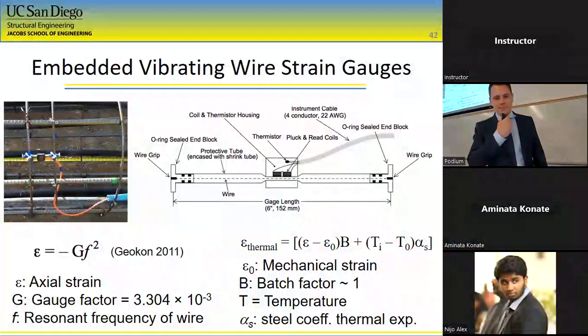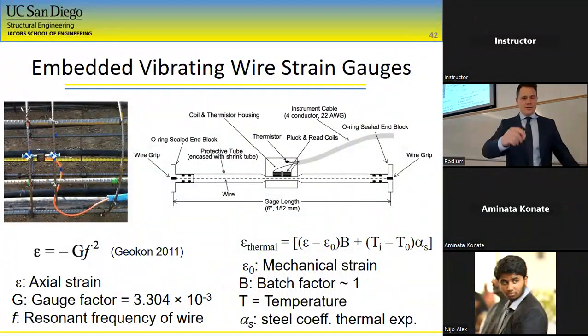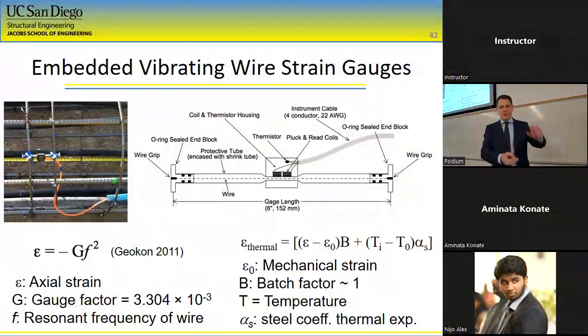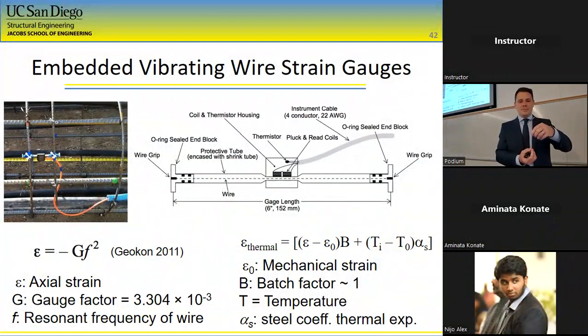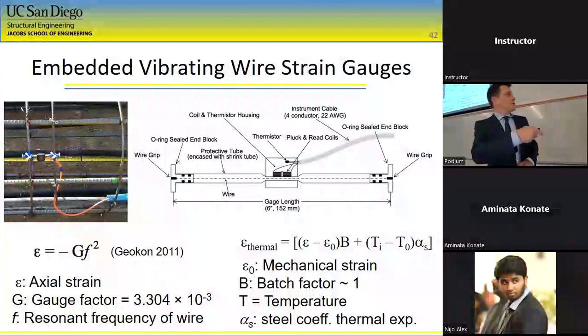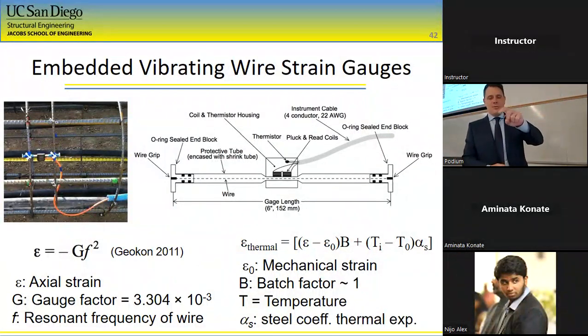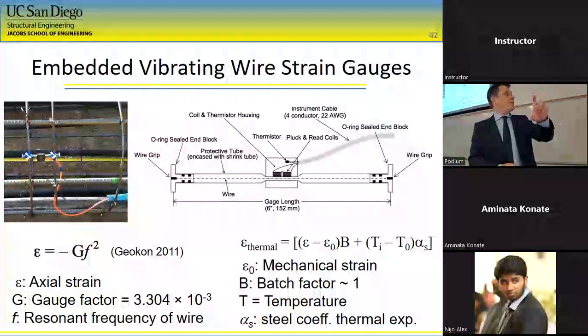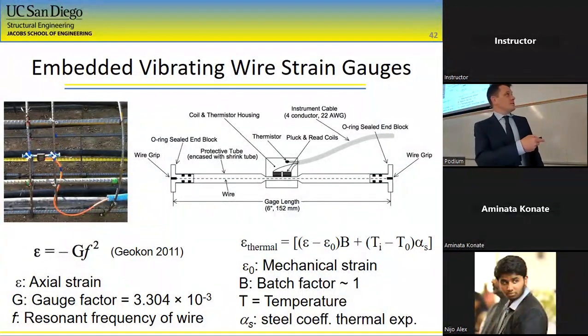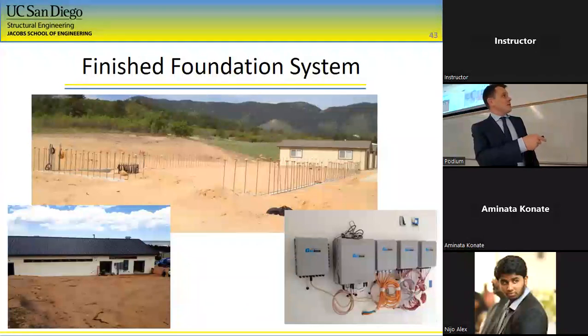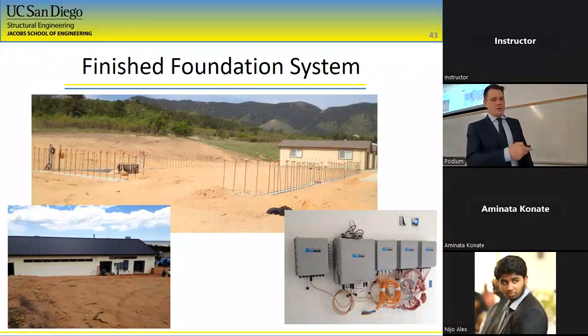And as I mentioned, we have the vibrating wire strain gauges on each of the piles at different depths. These are tricky because when you heat them, the wire is going to get longer. So it's going to make it look like the pile is going into contraction. Because if the wire is getting longer, it's like looser. So then the vibrating wire strain gauge plucks the wire and it's going to give a lower note because it's going to be a longer wire. So we had to do several thermal corrections on those strain gauges to make sure that they're adequately reflecting the actual expansion of the concrete. Then we had our grade beam at the surface, brought everything together to our electrical room, and built the building.